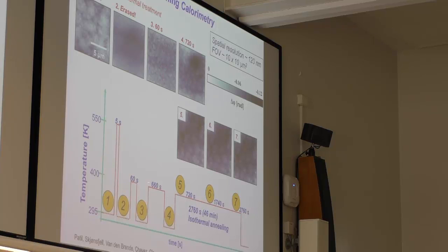structures are coming back gradually as we increase the annealing time. And the really fascinating thing about this is that you can really separate out the effects of the annealing time from the temperature ramping, right? Because in a traditional annealing experiment, instead of this line here, for example, just going straight down, you would have had something decaying slowly over time like this back to room temperature. Right, but with this technique, one can really quench the system back, and use this systematically to look at the formation of polymer structures.